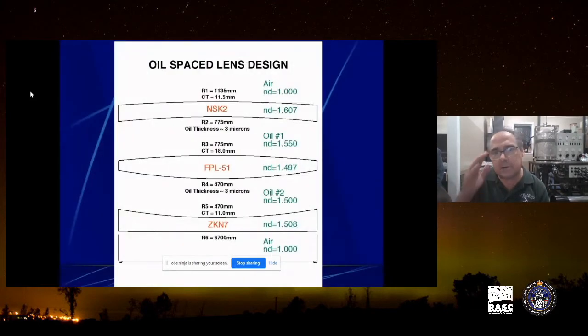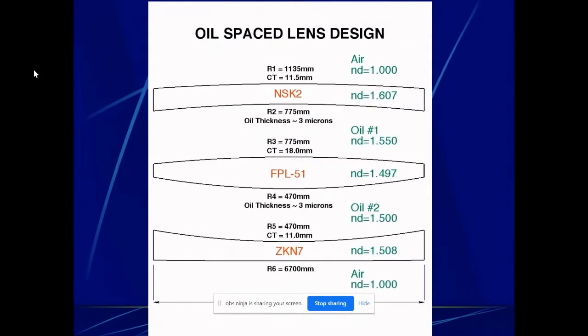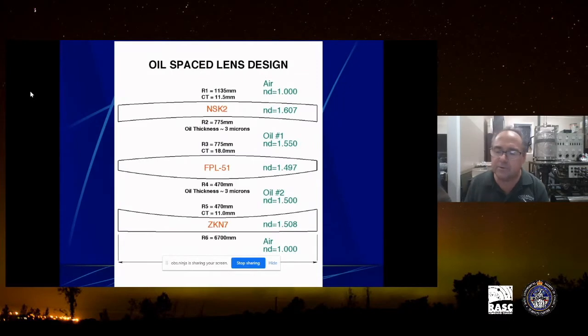Now, the oil is pretty expensive. It's about $150 an ounce, but you don't need very much of it to do the task. So basically, the lenses look like this. There are 3 different types of glass, and as you can see, they have different indexes of refraction. What we want to do is choose an oil that's in between the adjacent lenses so they best match. We want this glass to disappear when we put this oil in. That's what's nice about these oils. You can get them made to any refractive index you want, and that's why they charge the big bucks for them. So this is how it works. You can actually get away with just oiling these lenses and not have to do any coatings on them whatsoever.